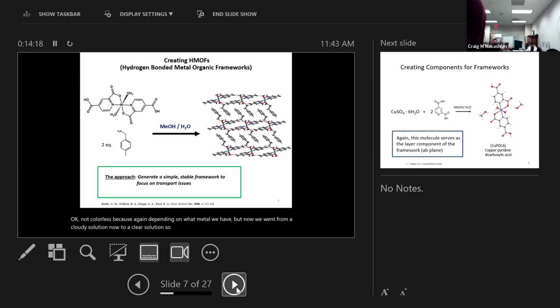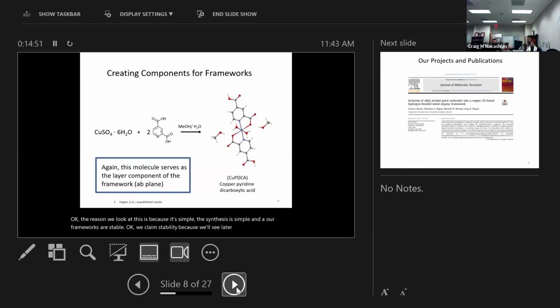So all of those solid particulates have now interacted with the amine and formed this charge-assisted hydrogen bonded species. So we technically have an inorganic salt in the grand scheme of things. The reason we look at this is because it's simple. The synthesis is simple, and our frameworks are stable. We claim stability because we'll see later in some data that we have frameworks that exist up to 200 degrees Celsius. Yeah, we can classify that level of stability. Okay, thermal stability. And that then allows us to focus specifically on our transport, the guest inclusion.